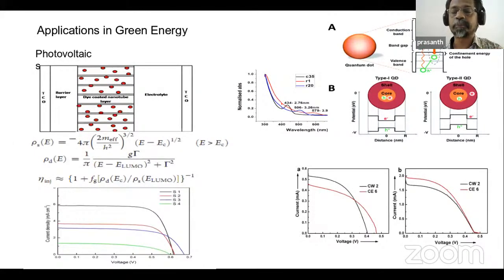But when we are really playing with a device structure, it is still showing a lower efficiency compared to a dye-loaded structure, because many other factors are influencing. It means the quantum dot is not really injecting electrons into the TiO2 nanotubes. If you are modifying its surface, in this case we used a type-II quantum dot structure, that is a CdS quantum dot structure, where you have a type 2 potential well structure. In a type 2 structure, the electron confinement and the hole confinement are in different layers of the quantum dot. Electrons are in the core and holes are in the shell structure, more or less like that. That way you can make a type 2 quantum dot. So that will make an easy separation of electron and hole pairs.